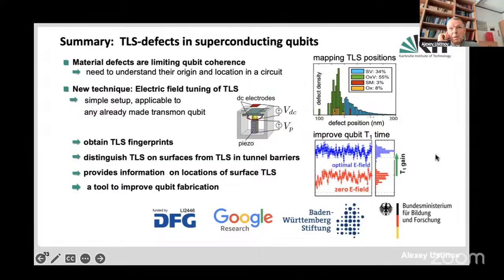Well, we came to this experiment empirically. So we decided to basically apply strain, and we did, applying some tens or even hundreds of volts to the piezo actuator. And this turned out to be sufficient to change the frequency in the range which you have seen in the data. Our calculation shows that the bending of the substrate, which means the displacement of the center of the substrate under the strain, is in the range of a micron, which would correspond to the relative change of the atomic distance in the substrate and also on the surface of the substrate, which means in the superconductor, by a relative factor of about 10 to the minus 7. So it's a variation, really very tiny. It's like you change the football field by a size smaller than the ball.